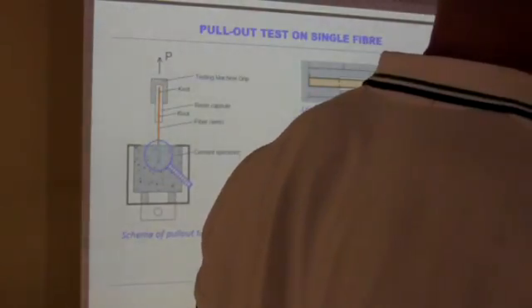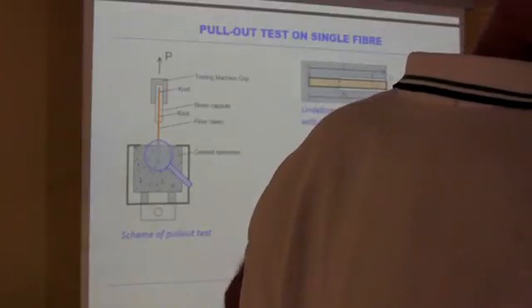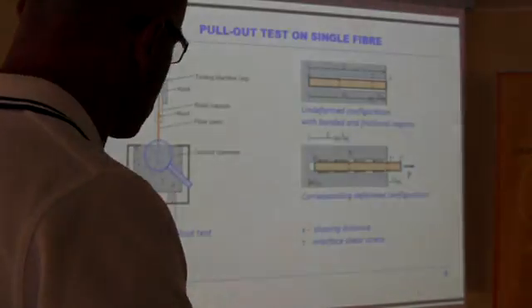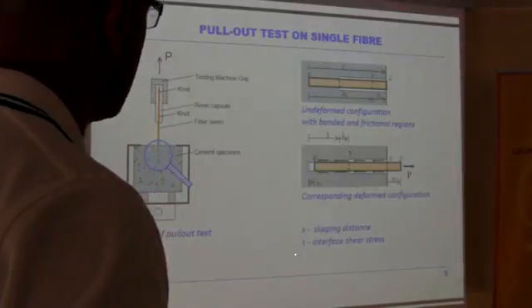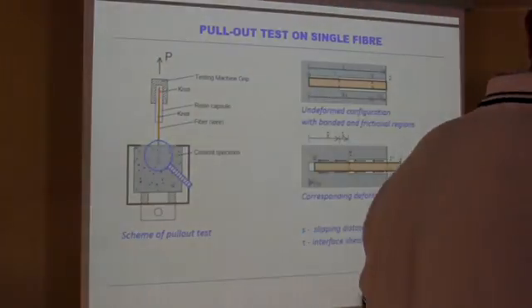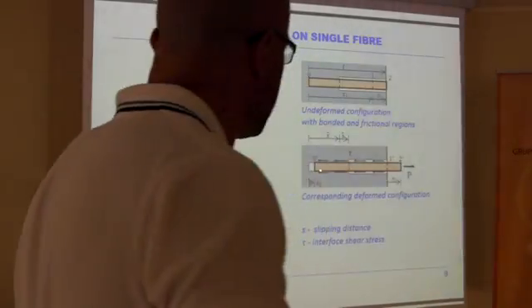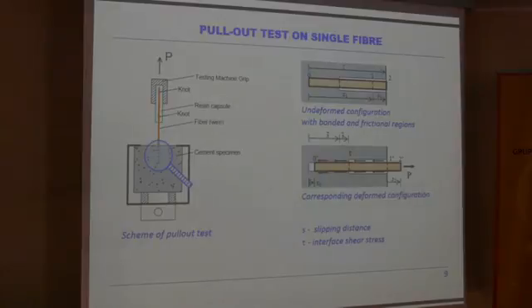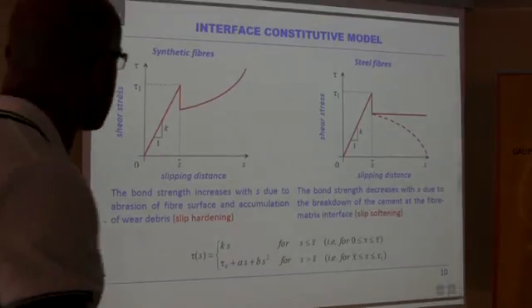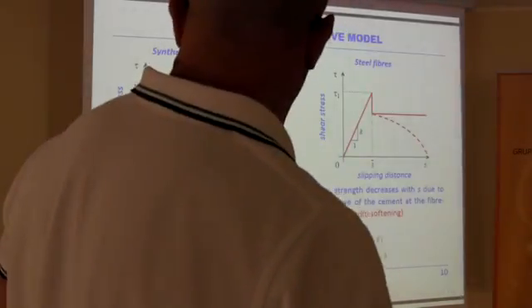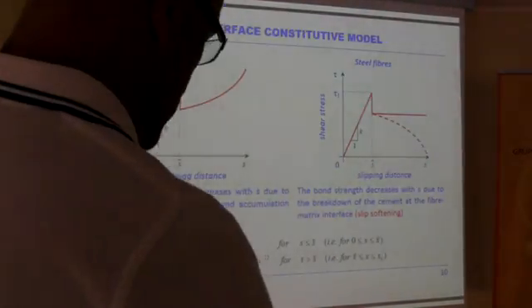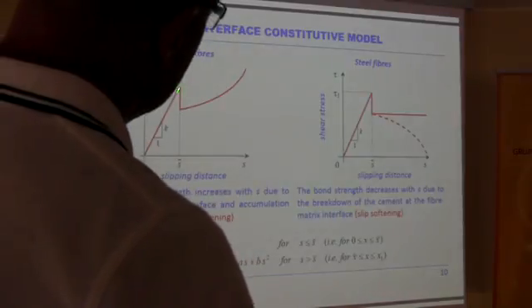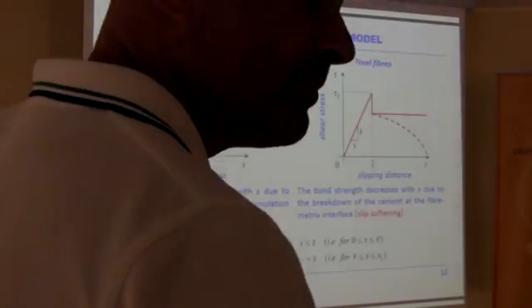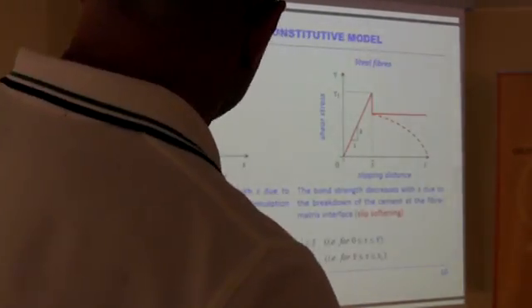And we also consider a deformed configuration where we set the balance condition, balance equation, and we denote with s the slip distance and with tau the interface shear stress, and these two variables are related by the interfacial constitutive relationship, which is sketched in this slide. For the interface constitutive model, we assume an initially linear elastic behavior in the bonded part of the fiber. Then the behavior is different for synthetic fibers or steel fibers.